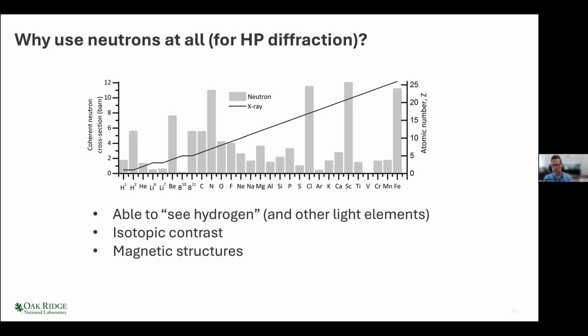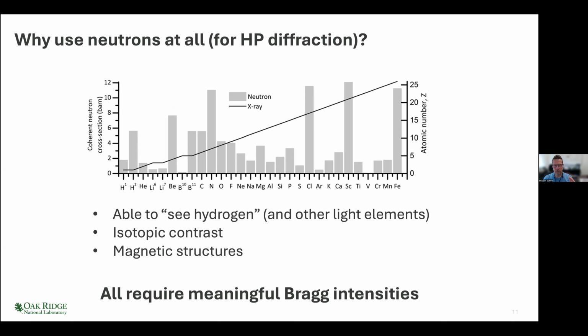And so you can actually do a Rietveld refinement or a single crystal refinement, and you can measure magnetic structure using neutrons. And this is where I wanted to make the point that to do all of these things, you actually need meaningful Bragg intensities. In the case of magnetic structures, you can identify magnetic phase transitions by just saying the magnetic peak is here, and now the magnetic peak is not here. That doesn't require accurate intensities, but everything else does. So it's very important to keep that in mind as you approach a neutron experiment and as you approach analyzing neutron data.